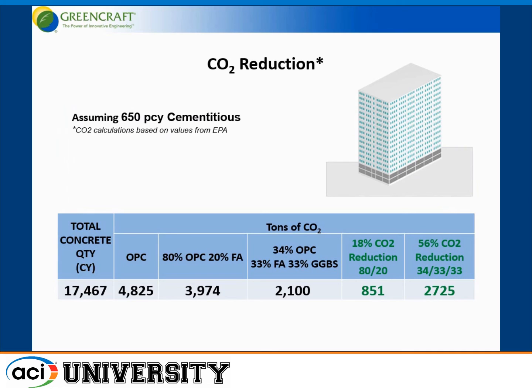If we take this building and on 17,000 cubic yards of concrete, ordinary Portland cement concrete mix would have about 4,800 tons of CO2 impact. With an 80-20 mix, you cut that down to 3,900 tons of CO2. But then you go to 1/3, 1/3, 1/3, you cut it by more than half. You're down to 2,100 tons of CO2 impact. This is assuming 650 pounds per cubic yard of cementitious material.